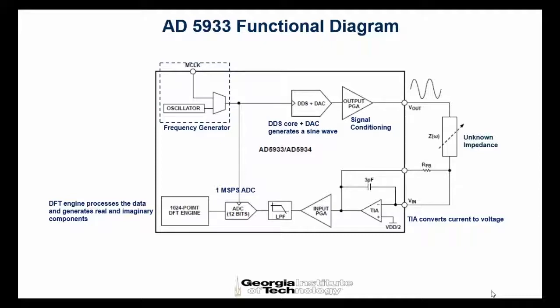Very briefly, you can find this information on the Analog Devices website, but very quickly, it's a digital frequency synthesizer, deriving a 16 megahertz clock and then synthesizing it to some digital signal, and that is converted by this DAC into an analog signal at a frequency between 1 kilohertz and 100 or 200 kilohertz. And then the signal is conditioned, and it goes through the unknown impedance. So this is the transmitter side. Then you have a transimpedance operational amplifier, which converts the current into a voltage. And then further analog to digital conversion, and then a DFT to read the bits and give you a complex number, magnitude, and phase.